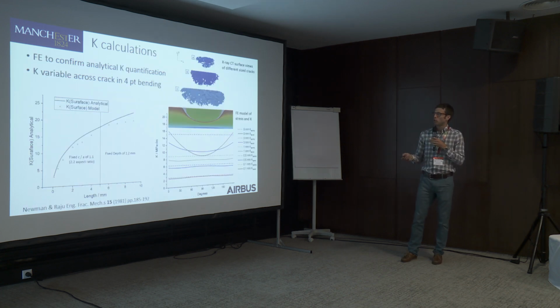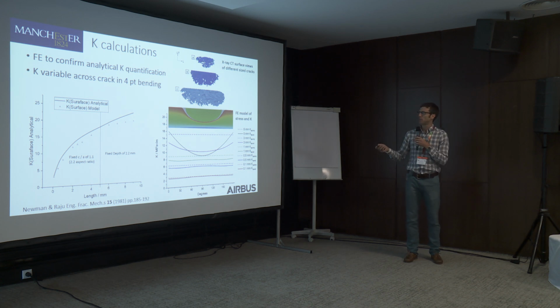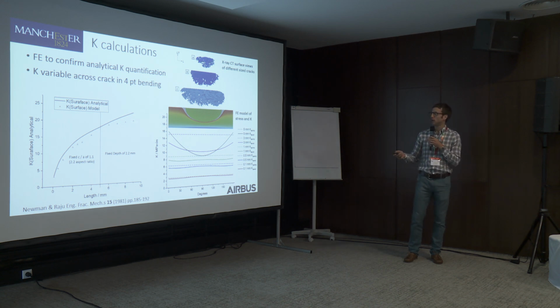So we've also taken these cracks. Here's some X-ray CT showing the shape of these cracks as they grow, because as they get much bigger, because it's a 4-point bend specimen, they start to grow into the depth, and the cracks in the depth start to slow down considerably, but when they're smaller they grow more consistently. But we've validated with some FE modelling the analytical approach of Newman and Raju that we've used here to measure the K across these cracks.